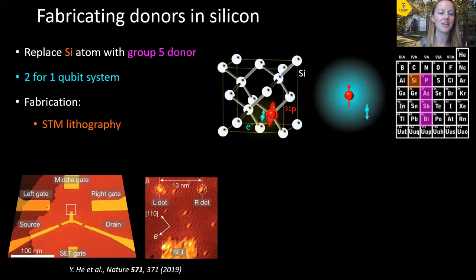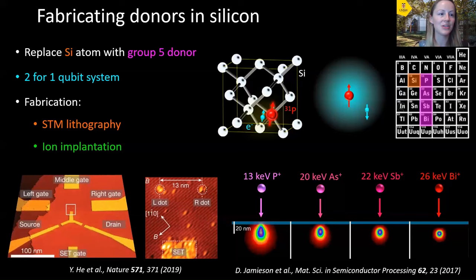And then another method is to use ion implantation to introduce your donor atoms in silicon. And this has a very nice advantage of being able to mass select from any of the group five donors. So instead of just being able to incorporate phosphorus into silicon, you could implant higher spin nuclei such as arsenic, antimony, and bismuth, and study more exotic physics with this. And so this is a really nice scalable pathway using ion implantation, as it's also compatible with semiconductor industry methods of fabrication.